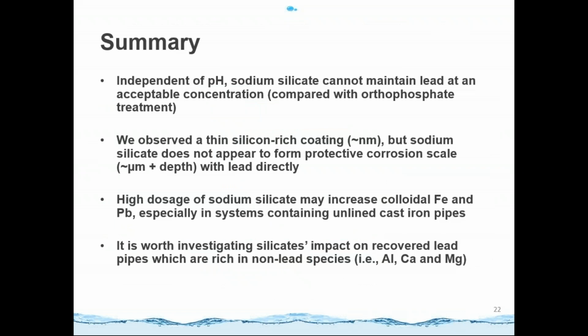It is independent of the pH, because in our study, we always maintained the pH of our system at 7.5. So at the same pH level, sodium silicate cannot maintain lead concentration at an acceptable level, especially compared with the orthophosphate treated system. And we did observe a thin silicon-rich coating at a nanometer level. But the silicon does not appear to form a protective corrosion scale like lead silicon solid with lead directly. So for the high dosage of sodium silicate, the overdosage may increase the colloidal iron and lead. So it's quite important in sequestration or lead release control.